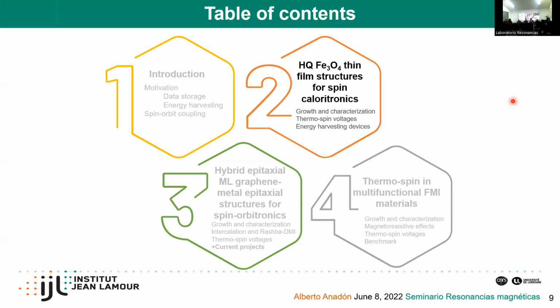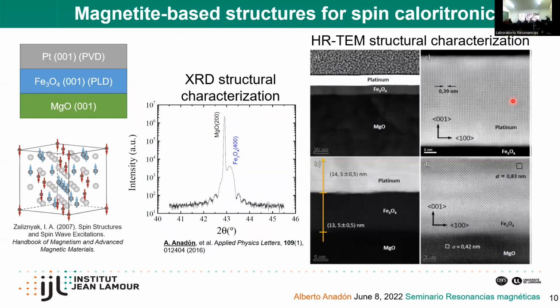So what I did during my PhD in Zaragoza, I prepared epitaxial magnetite thin films to study its spin current generation from incoherent thermal excitation. And I took advantage of this to generate charge current and power in a platinum layer attached to it. So basically, I was in charge of preparing these samples using pulsed laser deposition combined with sputtering in the same chamber in situ. So we were able to prepare high quality thin films of magnetite using different substrates and different systems. As you can see, with very clean interfaces, low interdiffusion and high crystalline coherence, as you can see from the low oscillations in this X-ray diffraction theta-two theta scan.